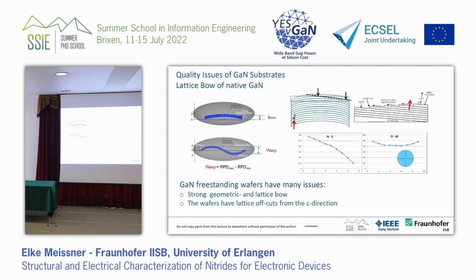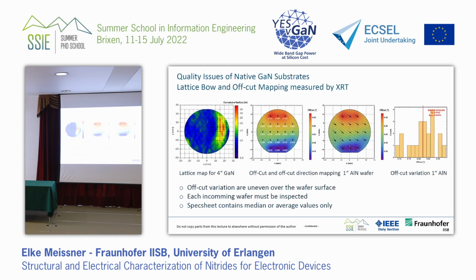So there are also more than just the front side to be considered, which offers the offcut to the system, where the atoms come and form the atomic layers, but also the back side. If the wafer is bowed like this, it will not stick in your epi pocket. So all the temperature, let's say the temperature contact from the backside that you need to heat the wafer up very evenly, and also the position of the surface will vary if your wafer is bowed like this. And this is all what you don't need in epitaxy, because this will compromise the quality of the epitaxial layers.